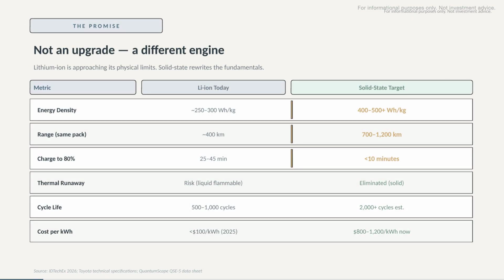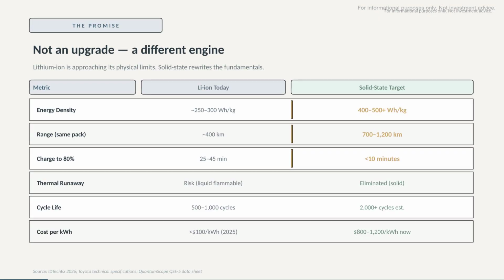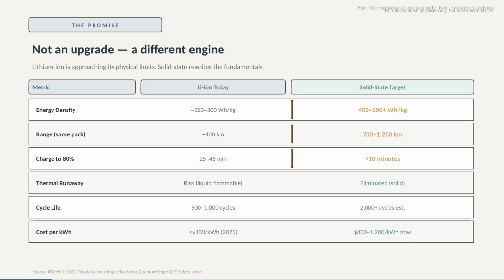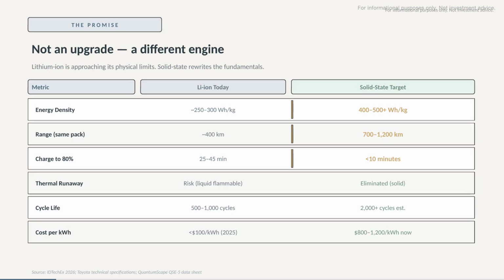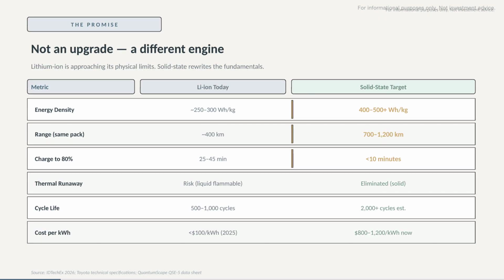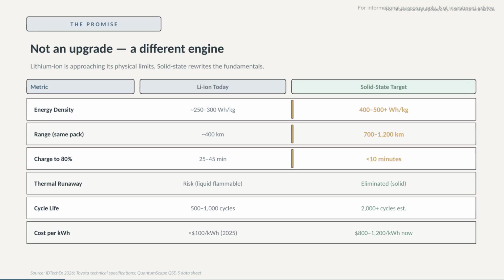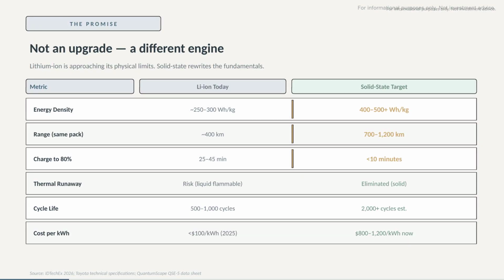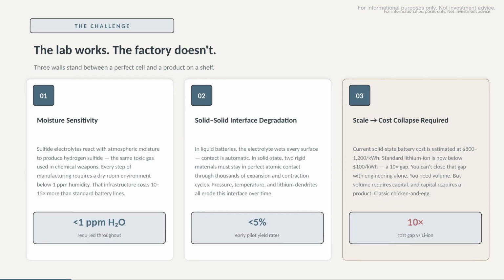Today's lithium-ion is hitting a physical wall around 300 watt-hours per kilogram. Solid-state targets 500, which doubles EV range. Charge to 80% in under 10 minutes. And the flammable liquid electrolyte? Replaced by a solid, thermal runaway essentially disappears. This isn't an upgrade. It's a different engine. Which is why everybody wants one. And why nobody has shipped one yet. The lab works. The factory doesn't.